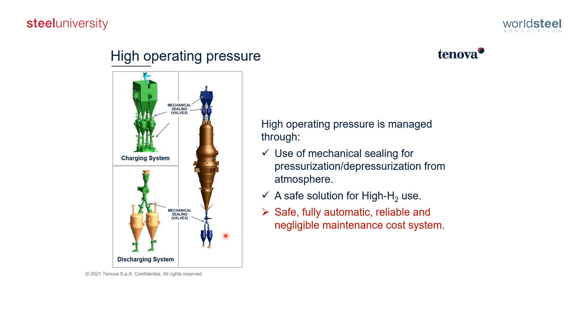So we don't use dynamic sealing trying to blow back the process gas into the module. We actually use valves to isolate the feeding area from the process area. You see there are vessels where the pressure is isolated. We charge the raw material into the vessel. We isolate each vessel and then feed into the module by rotating the four vessels. And at the discharge is just the same. There is a rotary valve feeding out into the buffers the processed pellets at high temperature. When the vessel is full, we isolate the vessel, we evacuate the process gas, and then we discharge the DRI